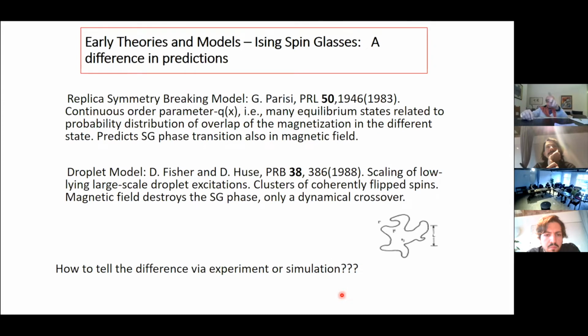But first, let me just look at what are these different predictions. Symmetry breaking says that there are many equilibrium states, with a probability distribution of overlap with the magnetization in a different state, and the replica symmetry breaking model predicts a spin glass phase transition at a magnetic field. When you apply a magnetic field, there is a spin glass. Daniel Fisher and David Huse say no, the application of a magnetic field quenches the spin glass state. It destroys the phase of the spin glass. So we now have a way to do experiment or even do large-scale computer simulation.